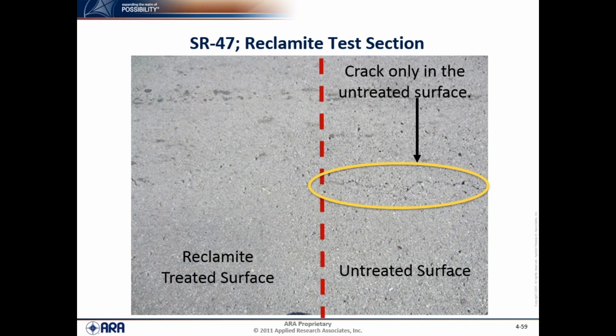The other item I want to point out is also on State Route 47. This is one of the longitudinal cracks, very minor hairline, but this is the untreated, and you can see the crack here, and this is the treated section. When it went to that edge, you didn't see the crack going into the Reclamite treated surface. After we saw this, we went back to some of the other sections and projects to see if we could find a crack in the adjacent section still going into the treated section, and we didn't find any. But I'm not saying that there is no cracking in the Reclamite section, because there is.